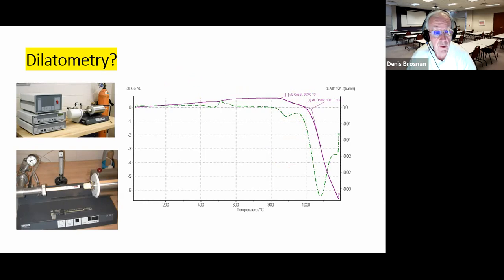So we can use these points of shrinkage, points of inflection, to tell us the temperatures at which we expect to fire the ceramic. So typically, if someone would come into my laboratory and say, well, here's a new clay that we're mining, and we want to mix it with another clay, maybe one clay for its refractory properties, lack of shrinkage, and one because it's highly plastic. Tell me what the mixture should be and what the firing temperature should be. And typically, we would resort to thermal dilatometry to get a first look at that question, and then later on make larger scale specimens, not something that's 20 millimeters long, but maybe quite a bit longer, bigger specimens, real size bricks.